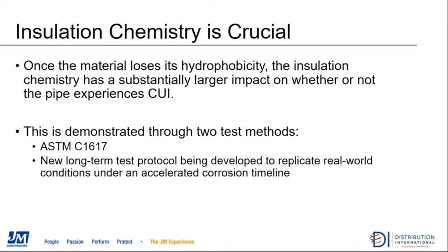So because in most instances these properties of hydrophobicity or water repellency are temporary, looking at the insulation chemistry itself is extremely important. You really need to look at a longer-term capability for providing protection against corrosion under insulation and minimizing the risk. And the insulation chemistry impact on corrosion is demonstrated through two different test methods that have been established. One is an ASTM test protocol, C1617, and the second is a newer long-term test protocol that's being developed by representatives from across the industrial sector.